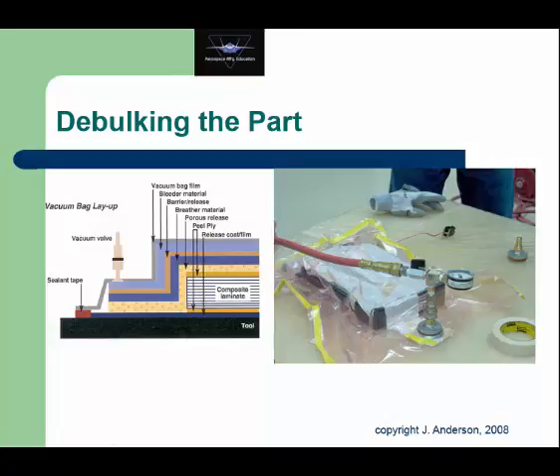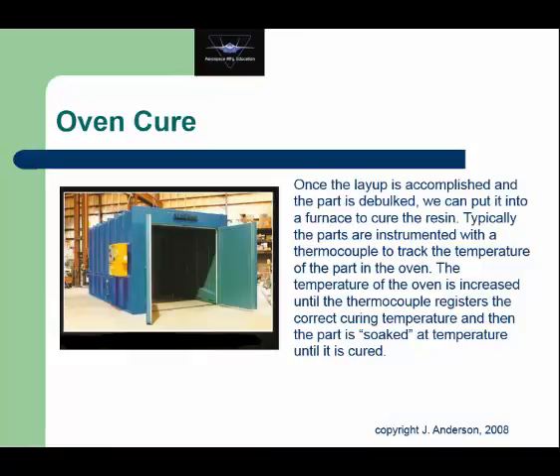So once we get it bagged, we need to raise the temperature in order to facilitate our cross-linking. Now, as we pull a vacuum, we're putting pressure on the top of the fabric and pressing it down into the mold, or consolidating the part. So for normal parts, that is not very high performance structural parts, we can sometimes get by with an oven cure. This is not a pressurized oven. This is just a normal industrial oven. And we take the vacuum bag part, we put it in this oven, and we soak it at temperature to get the cross-linking going. These ovens are characterized by fairly low temperatures, 200, 250 degrees Fahrenheit, and they are at ambient pressure.